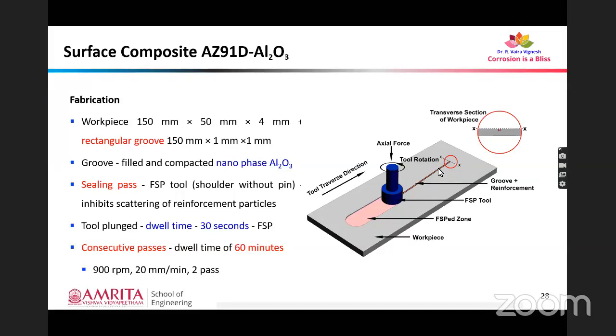And this process is enabled by forcing the tool towards the workpiece under an axial load. This is rotated at some rotation speed and it is traversed on the workpiece. So this rotation and traverse cumulatively creates the frictional force that results in generation of frictional heat that plasticizes the material. So that plasticized material flows from one part to the other based on the tool rotation. So that will give us an effective dispersion of reinforcements too. Added to that, there is mechanical fragmentation of beta phases in the matrix too. So we'll just see this microstructural evolution during friction stir processing in detail in the upcoming slides.